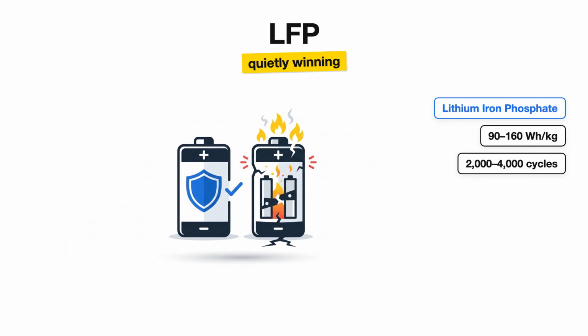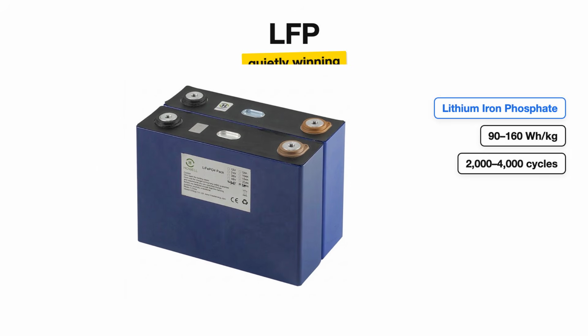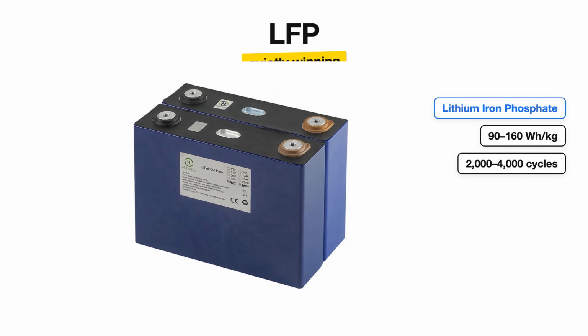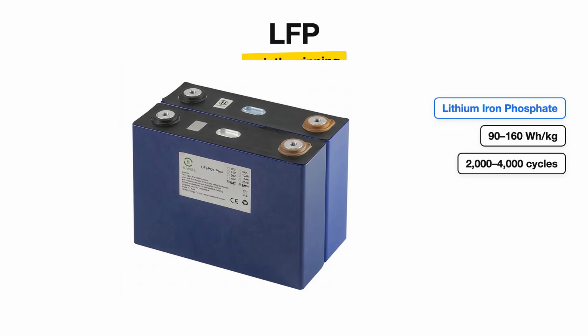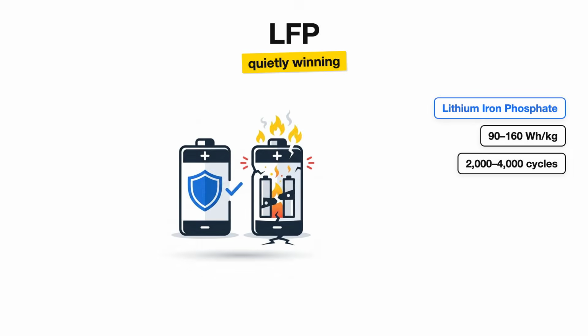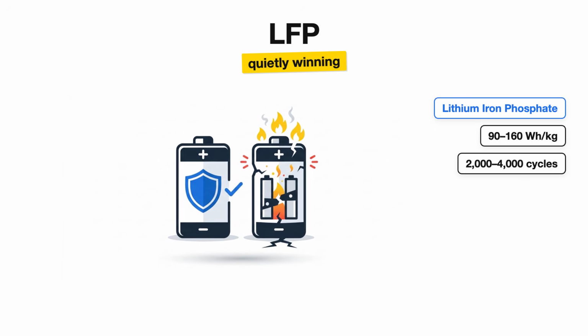The temperature at which an LFP cell enters thermal runaway, the dangerous chain reaction that can cause a battery fire, is around 518 degrees Fahrenheit. NMC cells hit that threshold closer to 392 degrees Fahrenheit. That 126-degree gap is enormous from a safety engineering standpoint.